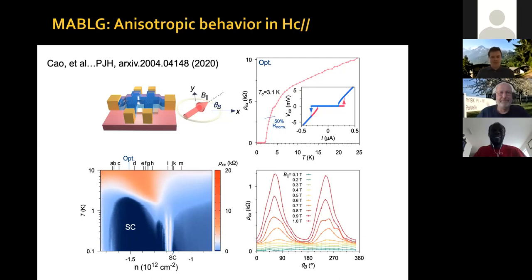Now, if you measure the resistivity as a function of magnetic field direction angle in plane, parallel to the magic angle graphene plane, we see these two maxima, okay? This means that the system is exhibiting C2 symmetry. It's exhibiting a response with the shape of an ellipse, okay? The system chooses a direction, okay? Now we can do this at different dopings, given by these letters, A, B, C, D, E, F, G, H, I, etc. Okay, let me show you in the next slide.